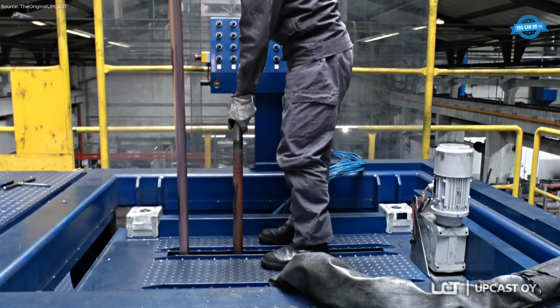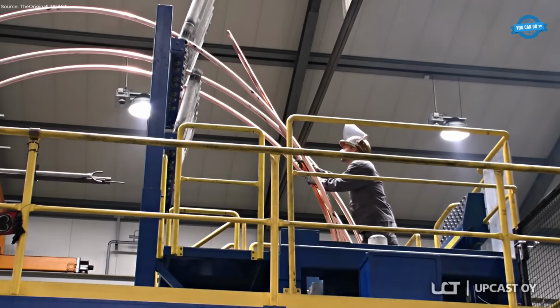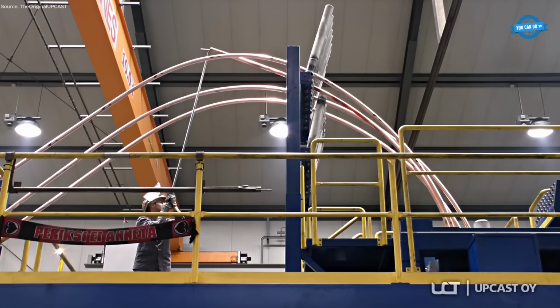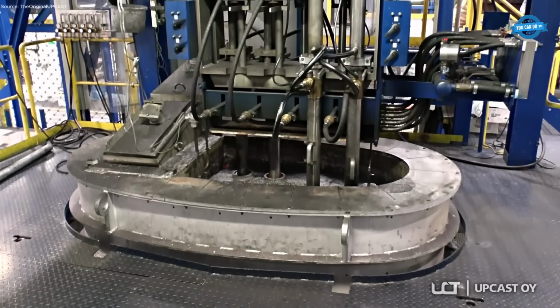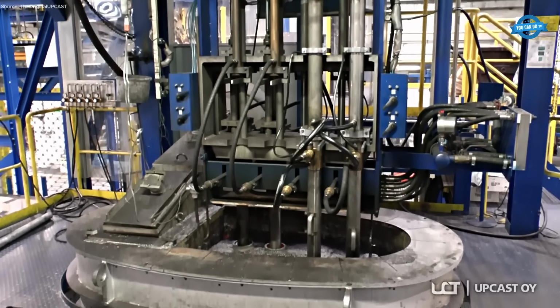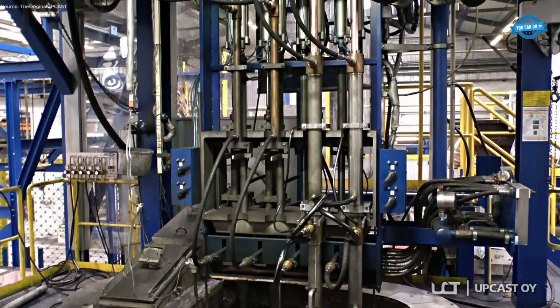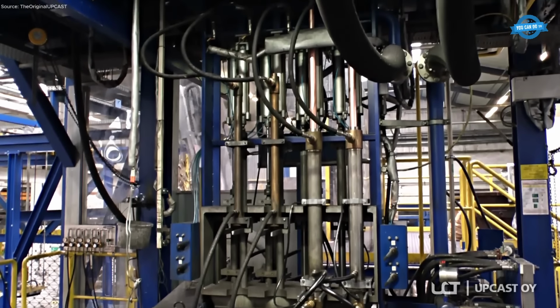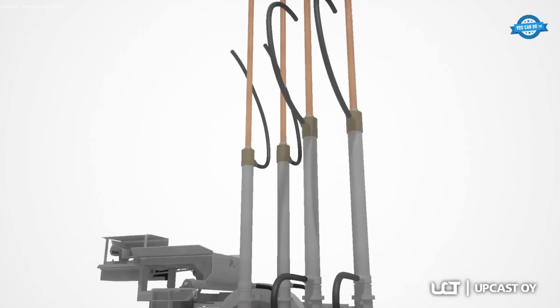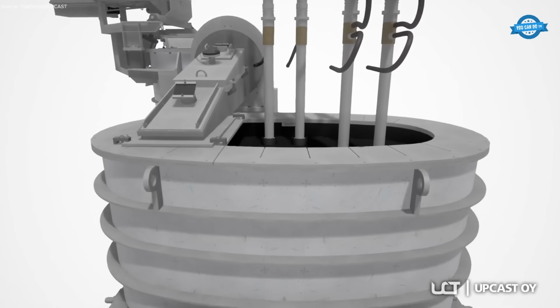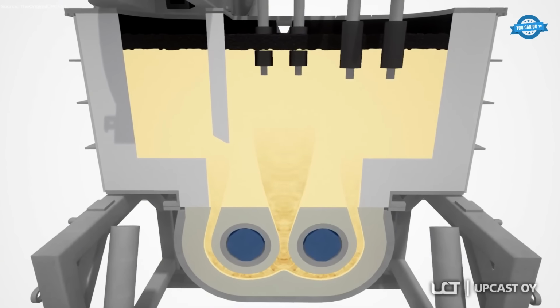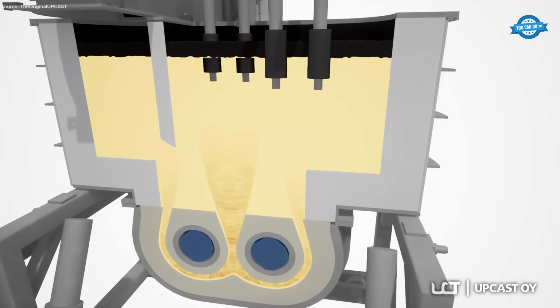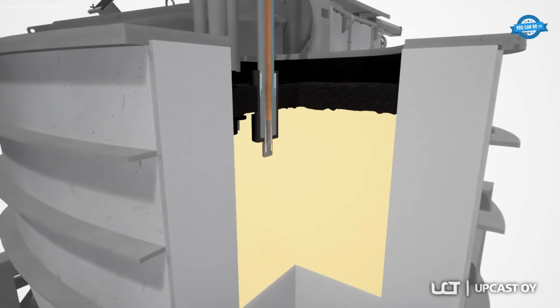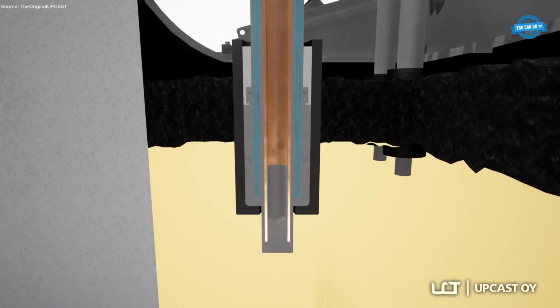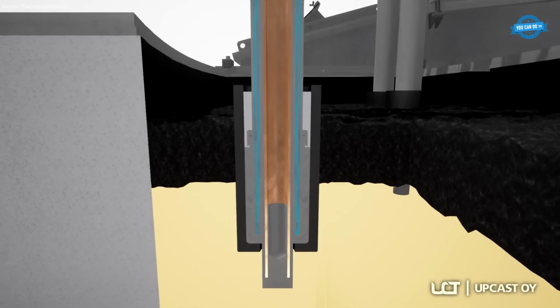The servomotor-driven pulling system lifts the solidifying tube or rod upward from the die, guiding it toward coiling equipment. Rods are typically collected using double coilers for continuous operation, while tubes are directed to single, heavy-duty coilers to preserve their form. The upward casting process produces a fine-grained microstructure with uniform wall thickness, ensuring excellent ductility, dimensional accuracy, and surface finish for downstream processing.